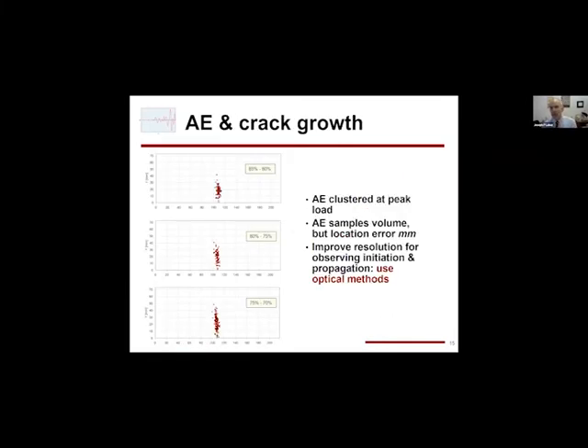Okay, besides just looking at what happens around peak load, we can use these events to monitor propagation. So now I'm showing results of locations into the post-peak region. So this is post-peak, 85% of peak load to 80%. So of course the load is decreasing because of this controlled fracture that is being followed using this closed loop system. So these locations are indicating a crack that's growing because of course we're prescribing this constant rate of crack opening displacement.